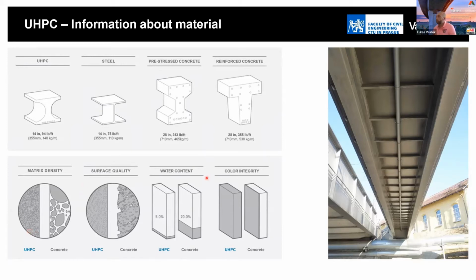Again, it is the question of the surface. UHPC compared to normal concrete: the surface of UHPC is completely closed. Normal concrete has hollows, very small cracks. And by these hollows and cracks, again, aggressive water could go through the concrete and attack the reinforcement, and some corrosion could appear. About the water content, as I said, the water content is very small in UHPC. We use normally approximately 5%, comparing 20% for the normal concrete.